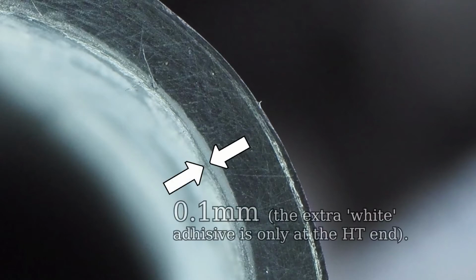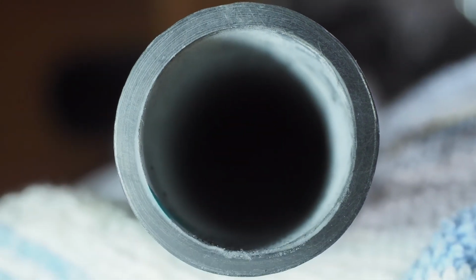Near the surface there's a layer of fibres that run around the circumference. On the inside diameter there's a layer of what appears to be glass fibre composite. This is about 0.1 millimeter thick. It's not thick enough to have any significant structural effect, so maybe it's there to aid manufacture. The good news is I couldn't see any defects in that section, neither lack of bonding between the layers or